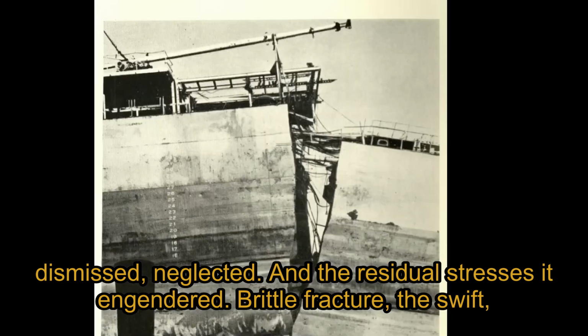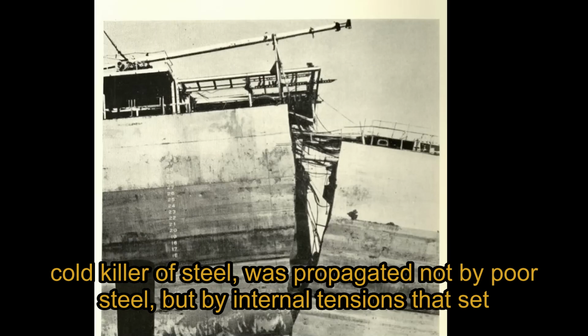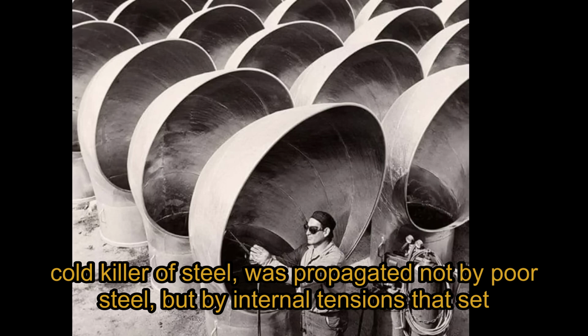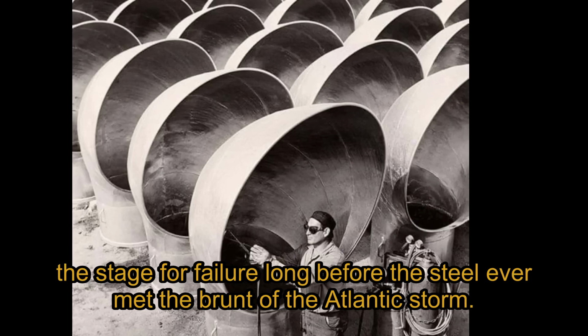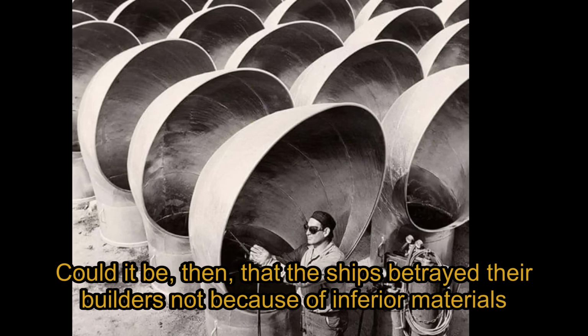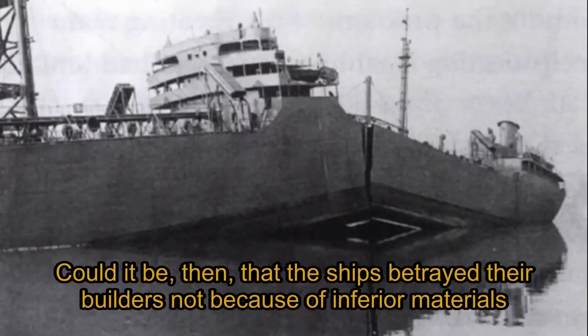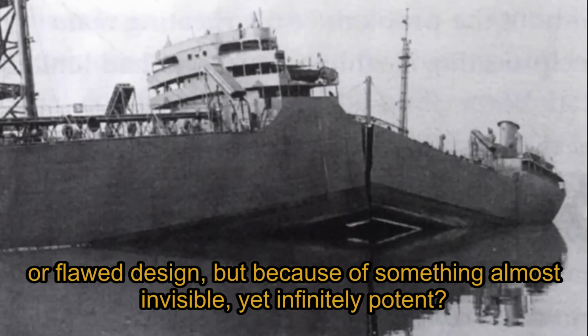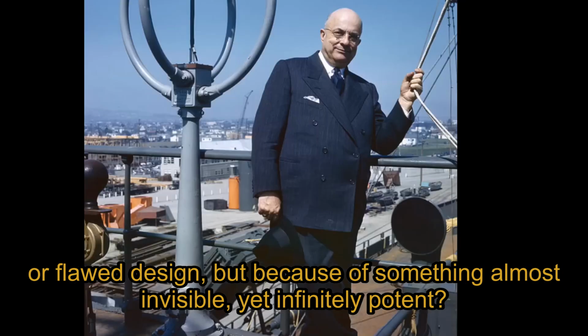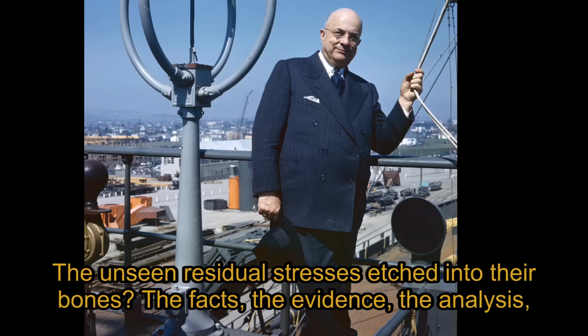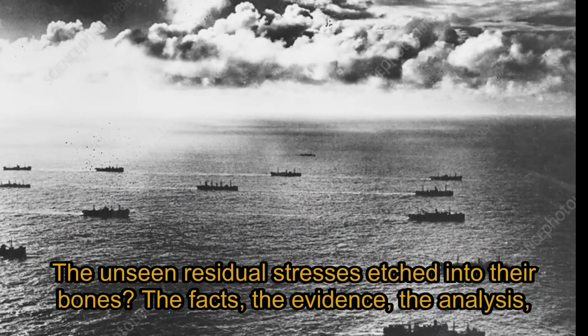Brittle fracture, the swift, cold killer of steel, was propagated not by poor steel, but by internal tensions that set the stage for failure long before the steel ever met the brunt of the Atlantic storm. Could it be, then, that the ships betrayed their builders not because of inferior materials or flawed design, but because of something almost invisible yet infinitely potent? The unseen residual stresses etched into their bones?